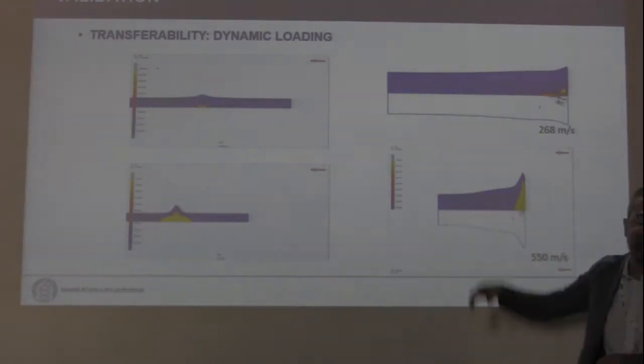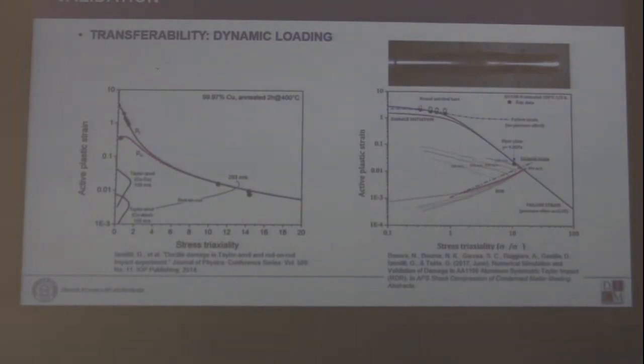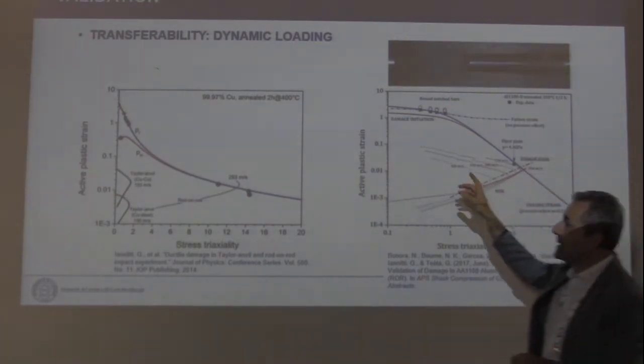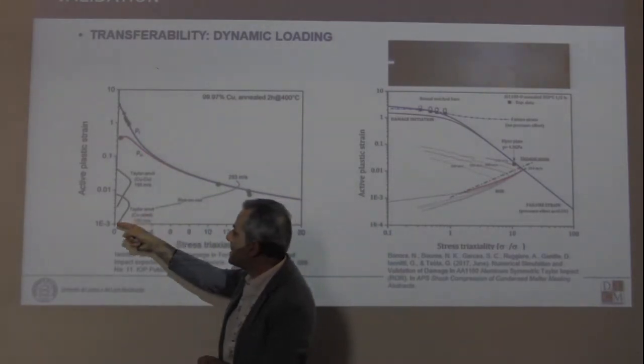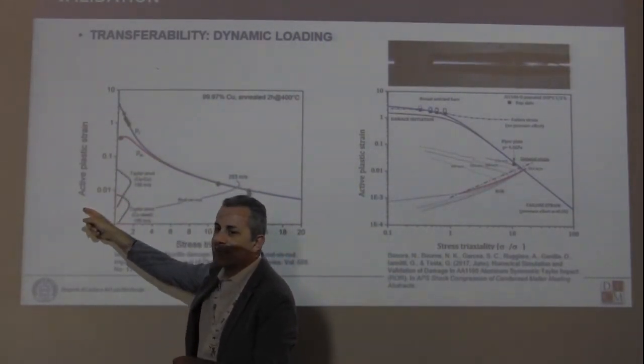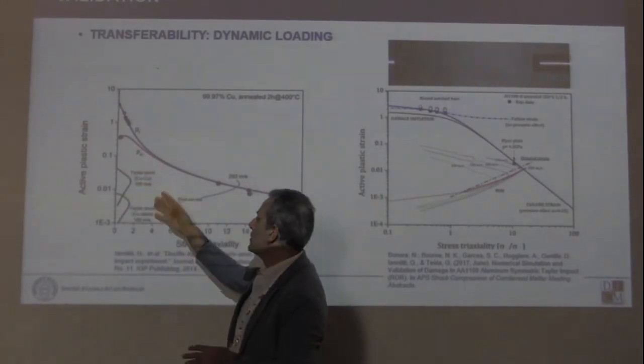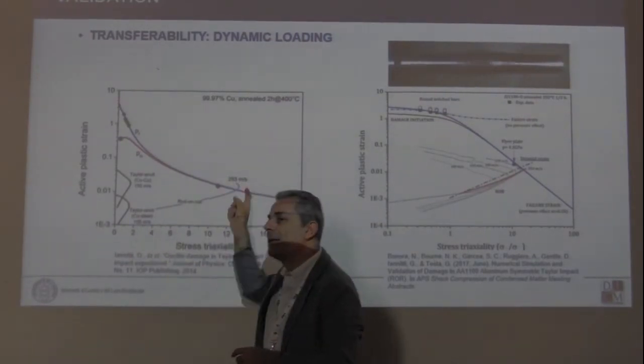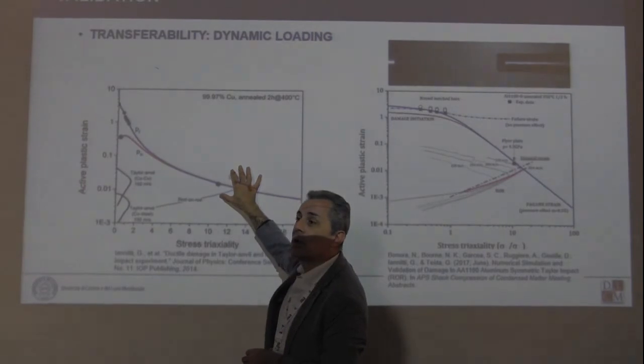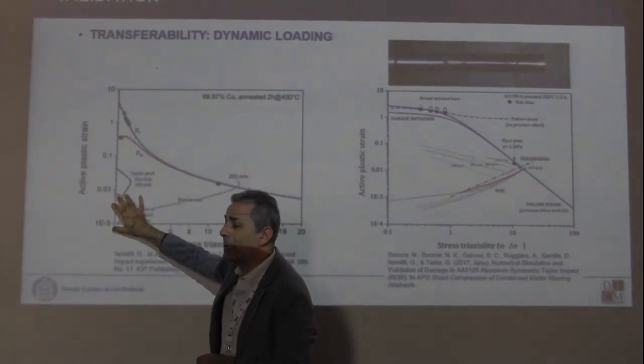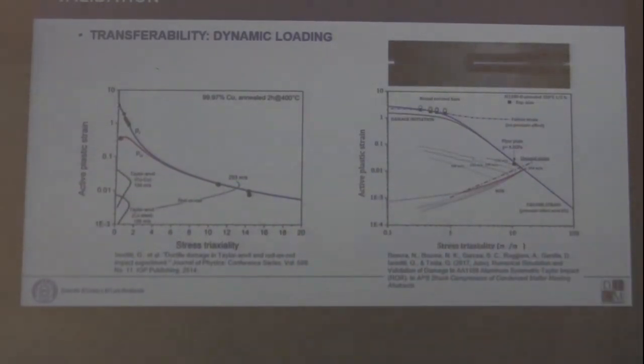To predict that in the second case, the rod-on-rod, which is the one on top in that video, in which you shoot a cylinder against another still standing cylinder, you generate a lot of damage. If you look at the problem in terms of stress triaxiality, this is the stress triaxiality evolution in time, and therefore in strain, for the Taylor impact. For equivalent conditions, the stress triaxiality for the rod-on-rod is a completely different stress path. So damage can occur in the rod-on-rod, while it cannot occur in the Taylor test. And we provided the rationale, and also the fact that the model was capable to predict this behavior, while other kinds of modeling specifically developed for high velocity impact failed to discriminate this behavior.